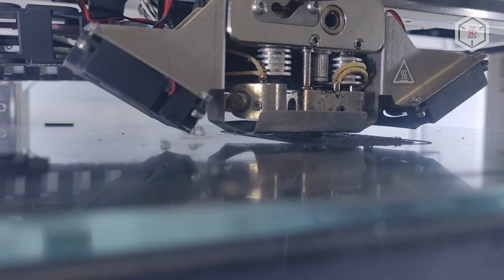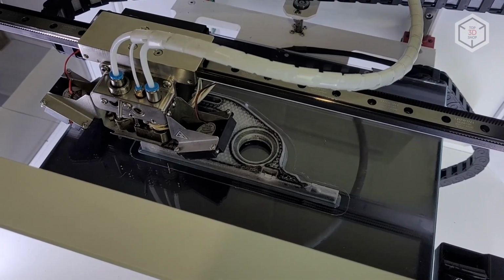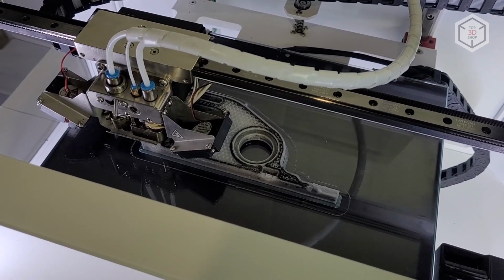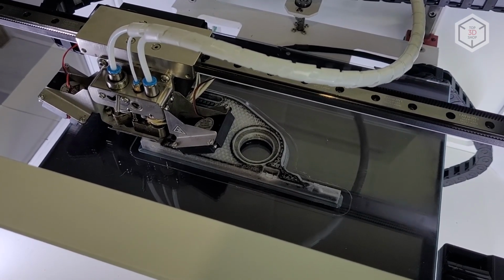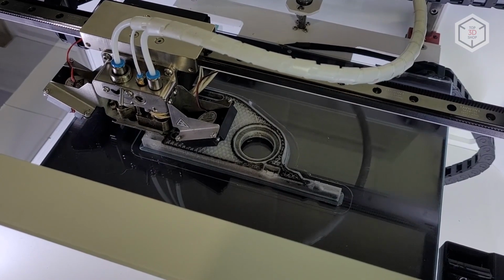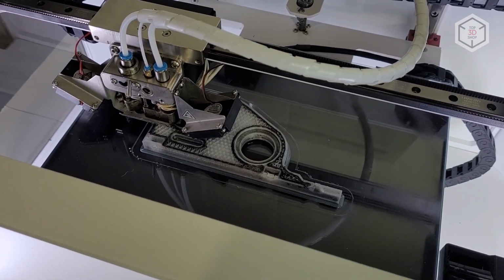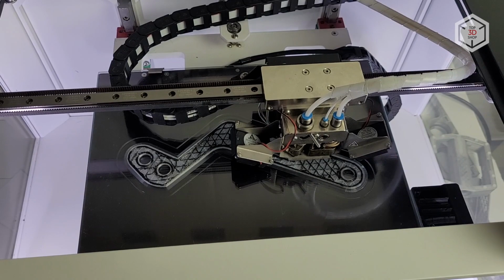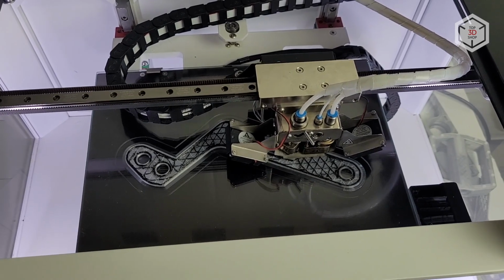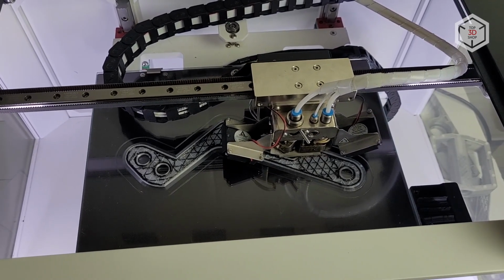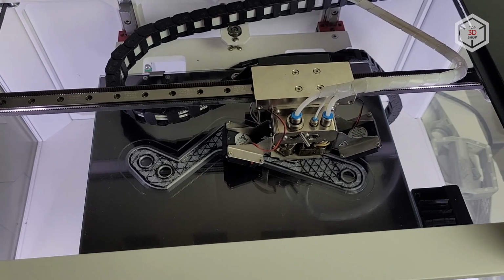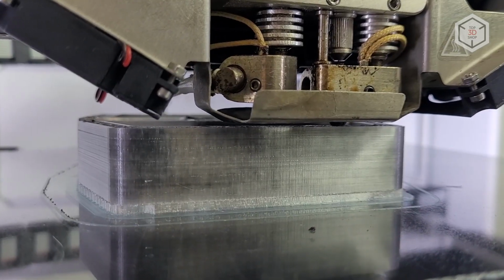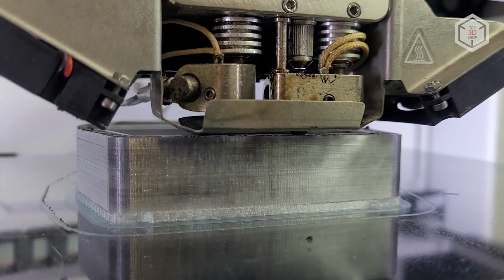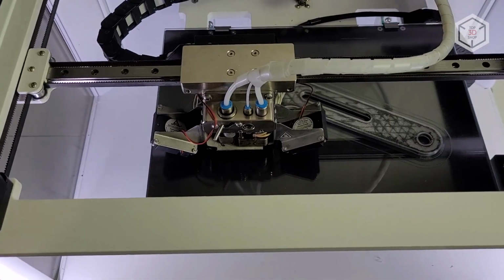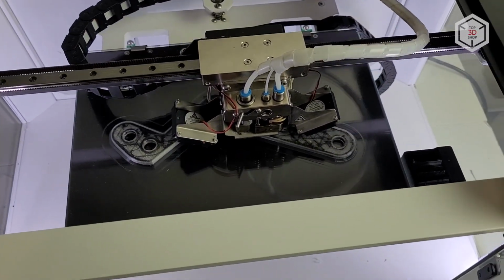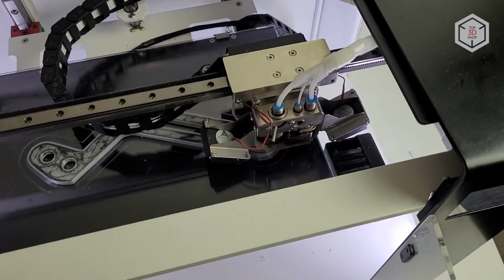With that being said, the printer requires a certain amount of skill. A single mistake in calibration may lead to a couple of hours spent on cleaning the composite hot end. Once we had such an experience. The construction of the composite hot end and the specifics of fiber placement require a good understanding of the process and proper model preparation for this printing method. If you need to print very strong lightweight parts reinforced with basalt or carbon fiber, if you are not afraid of the difficulties that can arise during operation, and you want to have access to all the features of the device and all the settings, then you will not find any analogs to this printer.